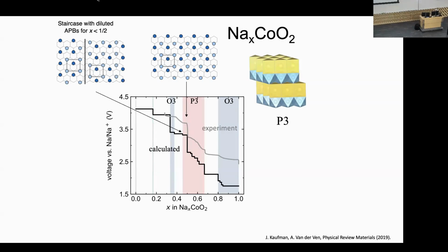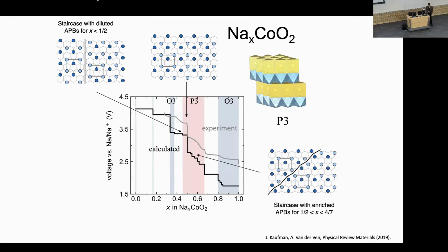But if you want to pull some sodium out, instead of just removing a few sodiums randomly, it would much rather form an antiphase boundary where you have the same ordering but shifted, and then you have an antiphase boundary where you have less sodium. And that leads to these little steps in the voltage curve. And that's a much more energetically favorable way of accommodating all these vacancies in this crystal structure. And you can do it on the other end as well. So you see this kind of staircase. And it's called a devil's staircase, because you can always come up with more complicated patterns of these antiphase boundaries.